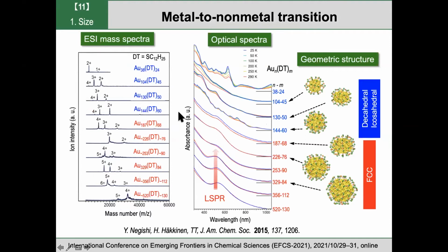And as you can see, this band, which we call the localized surface plasmon resonance band, disappears when we go below 187. This band comes from the collective oscillation of the electrons in the core. So if you see this band, you can say this particle is metallic. The absence of this band below 187 means that these clusters are not metal. And actually, you can see some discrete sharp structures. So this means the electronic structures are quantized. So the metal to non-metal transition takes place at this critical size. This is a very fundamentally important and interesting question we can address by size selective synthesis.